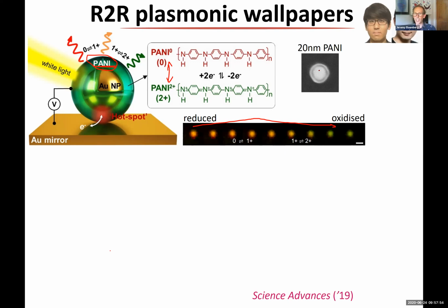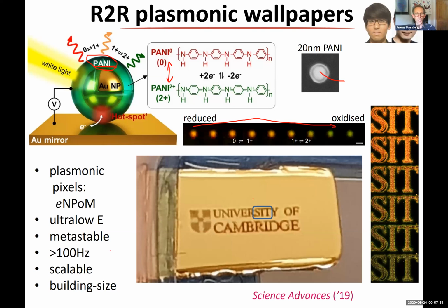The nice thing about this is that we can grow these in bulk quantities, and then we can assemble them and spray coat them onto a metallic substrate. So we actually scale this up. So these are sort of plasmonic pixels. We call them nanoparticle on mirror. And what we can do is we can just change the color by changing the voltage.